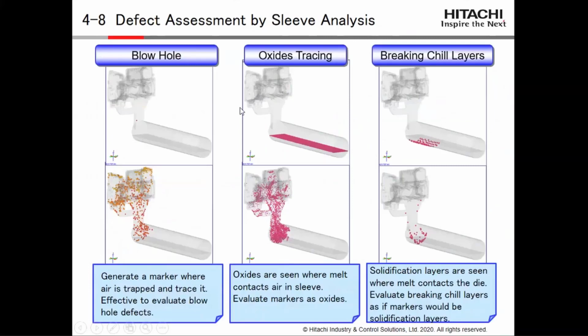So it shows the defect assessment by sleeve analysis. It shows the high pressure die cast method. So it is a product, and before entering it, we can simulate the sleeve area. And by visualizing with markers, we can evaluate the blowhole trajectory, oxide tracing, breaking chill layer, and so on.